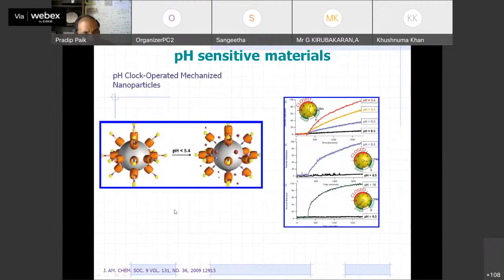So you see, pH sensitivity. Let's say this hollow core is showing like a key. When pH is low, they close this pore, and above this pH, they open the door of this channel. Then what happens? Below this pH, you can load easily. So drug molecules will go in and be entrapped inside this core. Increase the pH, and the size will expand, then drug molecules will come out. So in these cases, it is entering, and in these cases, it is coming out.